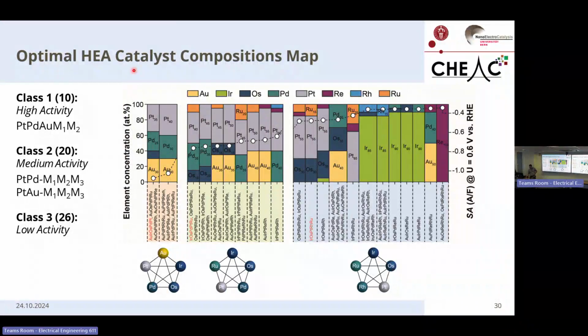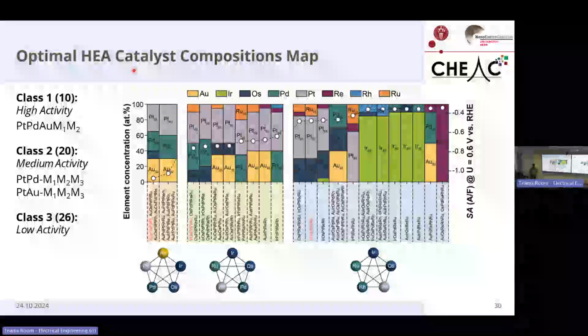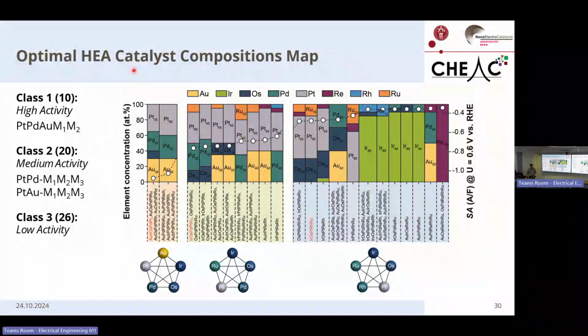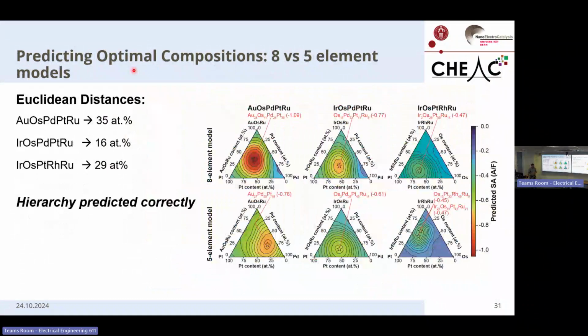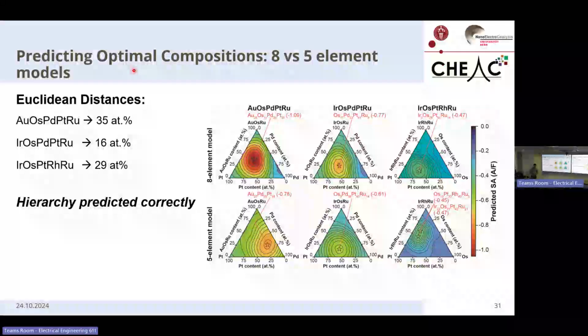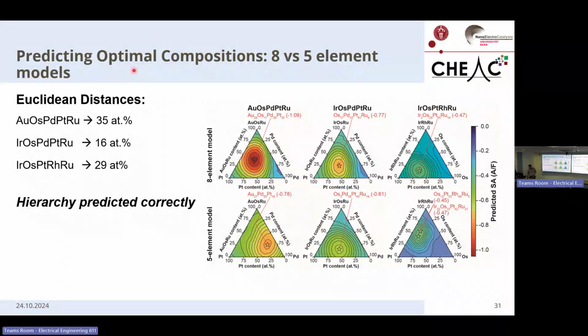Conveniently, it also turns out that the 3 investigated spaces each belong to a separate activity class. So we can take a look at how well the 8-element model can predict the activities. And now we see that there is a large discrepancy. In gold, osmium, palladium, platinum, ruthenium, the 8-element model predicts that osmium is part of the optimum, whereas the 5-element model tells that that is probably an artifact. Likewise, in the least active space, the iridium, osmium, platinum, rhodium, ruthenium, the 8-element model predicts a single optimum, whereas the 5-element model predicts that there are 2 optima.